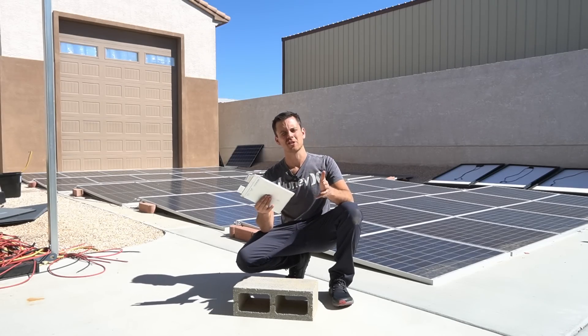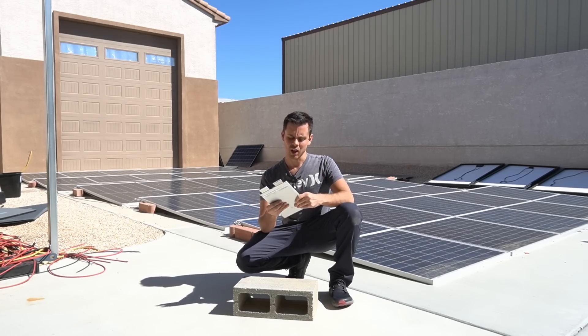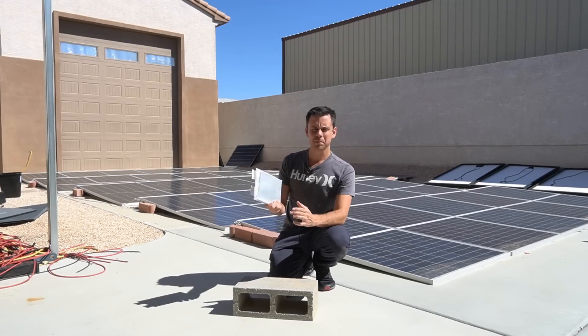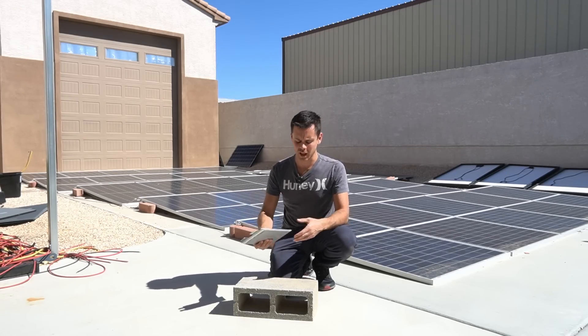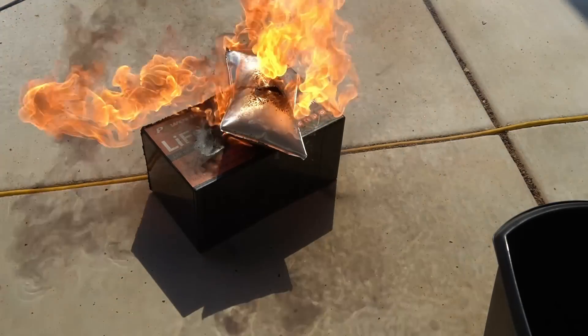This time I'll have better protection gear. Now the reason we use lithium iron phosphate in solar power systems, especially for residential use, is that they're very safe — it doesn't have a self-propagating thermal runaway event. The electrolyte can still combust, so it has a very slow burn if you catch it on fire. This is because of the thermal stability of lithium iron phosphate: when it reaches high temperatures, it doesn't release its oxygen, meaning further heat is not generated to cause the reaction to self-propagate. If you look at a graph of how much energy is released by different lithium-ion chemistries during a thermal runaway event, lithium iron phosphate pretty much has a flat line at the very bottom. All the cobalt-based ones release lots of oxygen that reacts with the constituents — a massive amount of heat is generated, more oxygen is released, and then you have a fire inferno.